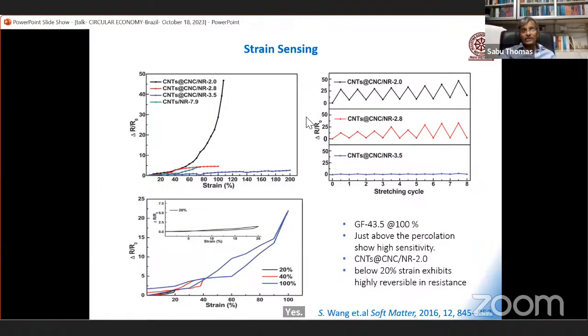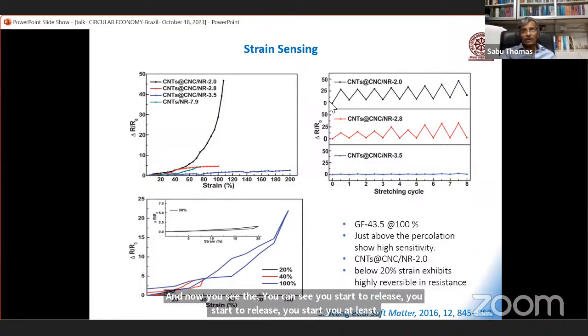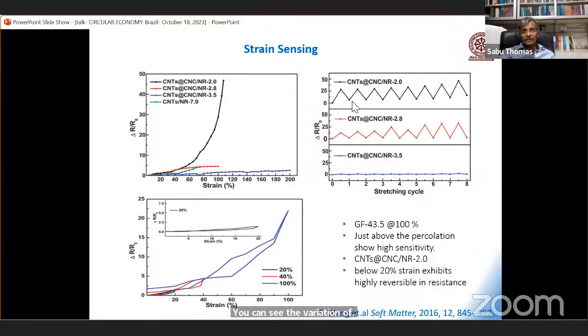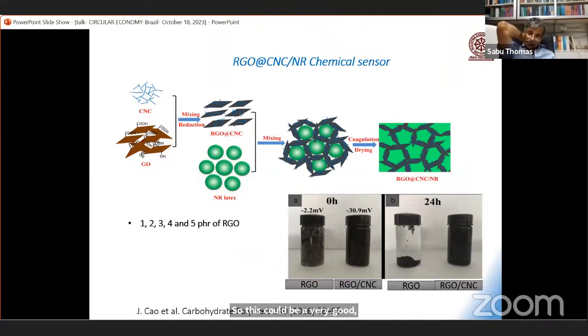Okay. And now you see the strain sensing. You can see you stretch, you release, you stretch, you release, you stretch, you release. You can see the variation of electrical conductivity. Decrease, increase, decrease, increase. So this could be a very good sensor. Similarly, dear students, we can combine nanocellulose and reduced graphene oxide. We can combine both. This is CNC and this is graphene oxide. You mix them together, mix with the natural rubber latex, and then you coagulate and dry it.